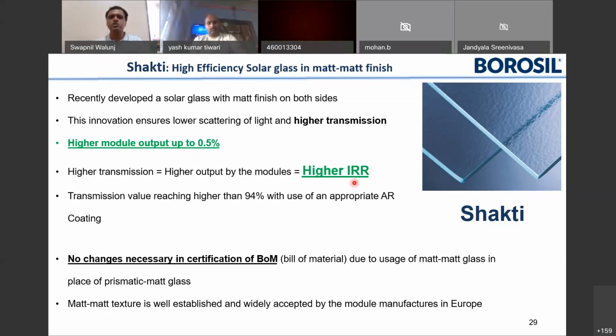If we use the proper anti-reflective coating, we are able to get a higher transmission, higher than 94%. And the best part is there is no change necessary in the bill of materials, so you can directly use matte glass as it is for module manufacturing without any change of certification. There are many countries in Europe that have used matte glass, which seems to be a standard there.